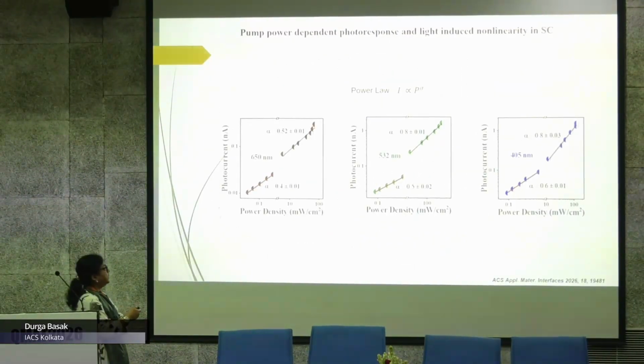We know that in case of photocurrent, it follows I photocurrent proportional to P to the power alpha, where P is power. Alpha is the parameter which defines how the carriers are separated. If alpha is 1, it is good, the electron-holes are quickly separated. But if alpha is less than unity, then there is trapping. So here we have plotted power density versus photocurrent, which says that at low power the alpha is 0.4, whereas at higher power it is 0.52, and for all the wavelengths, for lower power the alpha is much less than unity, but at higher power it is somewhat near to unity.